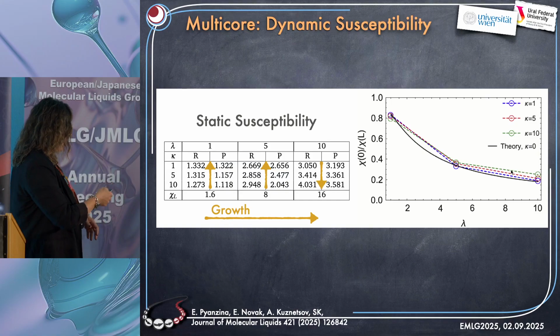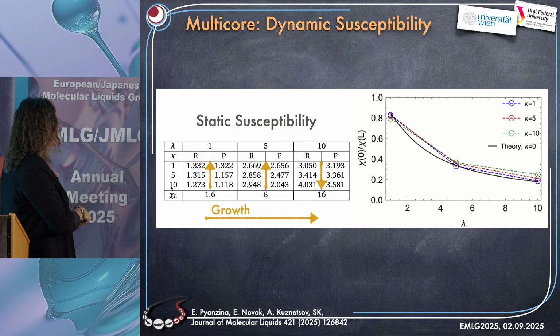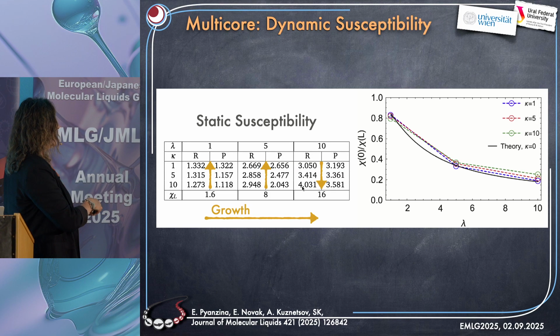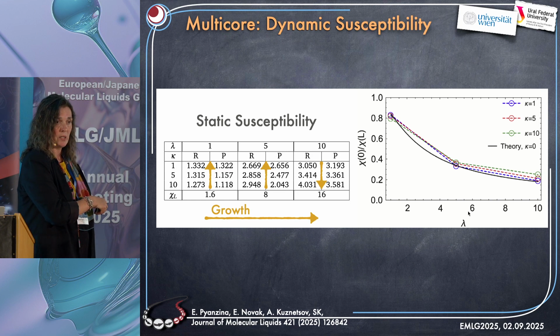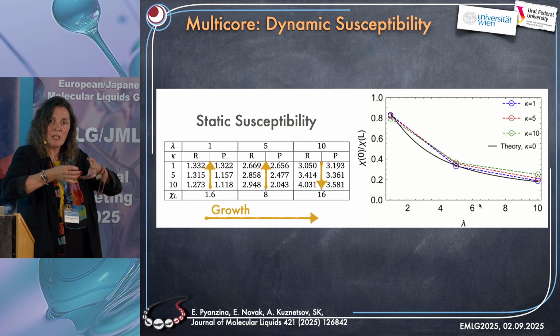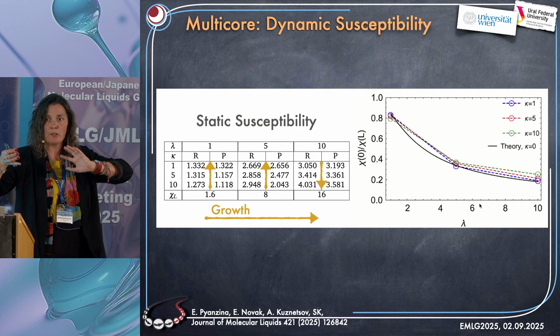And if you look at this part, you will see that the anisotropy has the same effect if the interactions are weak. But if the interactions are strong, the anisotropy leads to a slight increase in susceptibility, because it blocks the interactions, so it keeps the dipoles inside relatively disordered.